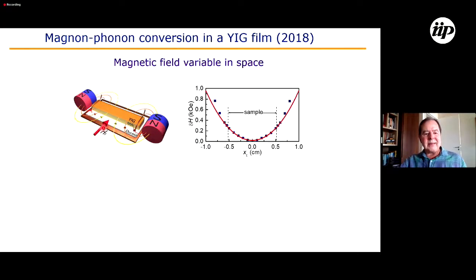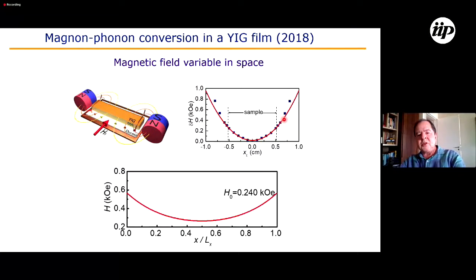And the sample is also in a static field. This is the field of an electromagnet, and this is the field of two small magnets. And by measuring the field between the two magnets, we have these points here, and we can fit a curve to these points so that we have a polynomial expression for the field. And of course, the value of the field varies at each point of the film, and it also varies with the applied external magnetic field. So for an applied field of 0.24 kilooersted, the internal field in the sample is given by this value here because of the contribution from the two magnets.